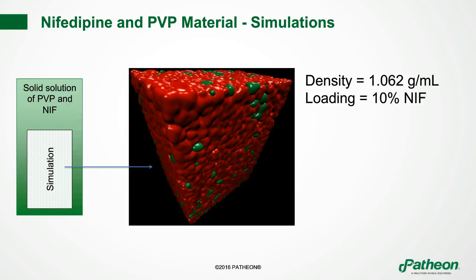Now, the density of this system was calculated to be 1.062, and that's actually very close to the actual density that we can measure for this, and you can measure this with a lot of different methods. Stereopycnometry is one method that you might choose. But the density that we've calculated is very close to the actual density that we've measured for this system.